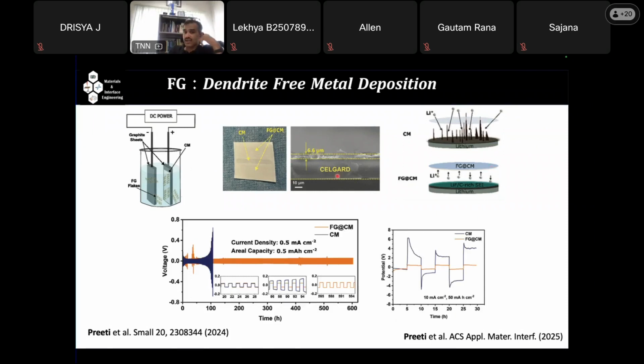We knew that the material which is helping for lithium ion transport is lithium fluoride. We know it a priori now, because we studied it, and not only us, various people have understood that it's lithium fluoride. Can you deposit lithium fluoride? Because lithium fluoride is a well-known material in photovoltaics. They use the same lithium fluoride deposition in solar cells, etc. Now, can I use the same lithium fluoride a priori before you make the electrode? It is not possible, because the lithium fluoride needs to be formed in situ.